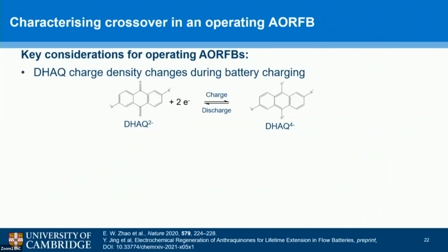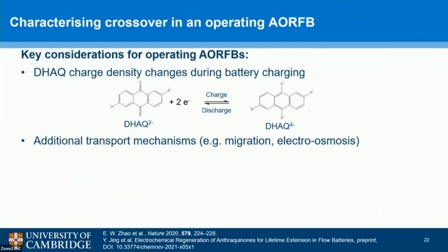For a start, when we are charging the quinone, we're actually changing the charge density. So we're going from a 2- into a 4- state. And you can imagine that as we're using a cation exchange membrane, you'd expect this to increase the repulsion and therefore potentially reduce crossover.